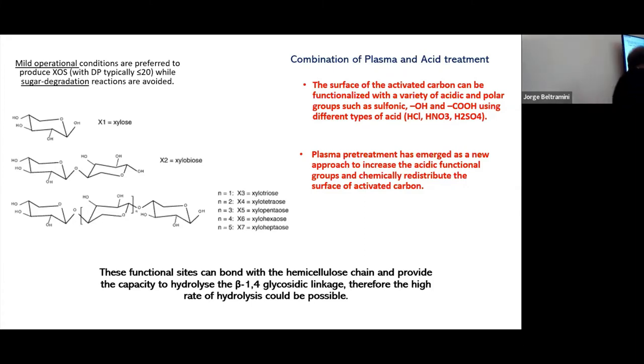Okay, the idea was, why don't we use plasma treatment? We need to produce an activated carbon with acidity function, a moderate acidity, in order to break down that molecule of the hemicellulose and get high selectivity for these 3 compounds. One student came with the idea to use plasma technology. And we said to him, okay, if you do plasma treatment on the carbon, and then you do the acidification of the carbon, put the acidity into the carbon, we see what we can get.